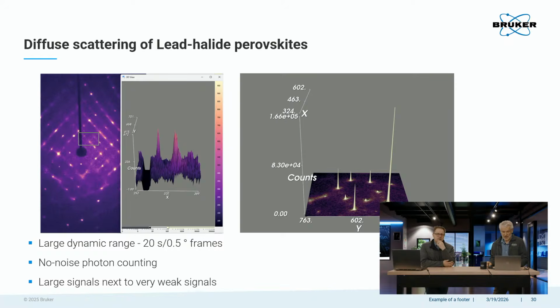So here, in this case, what they're interested in is to look at these very weak signals next to very strong signals. Here, if you can appreciate the little square, it's a rectangle, and then this is the 3D view of it. You also can see the black, that's where the hole in the beam stop is, and then you have these very, very weak diffuse scatter. These scales are a little deceiving, but we have to use them to show reflections that are orders of magnitude stronger. Wow.